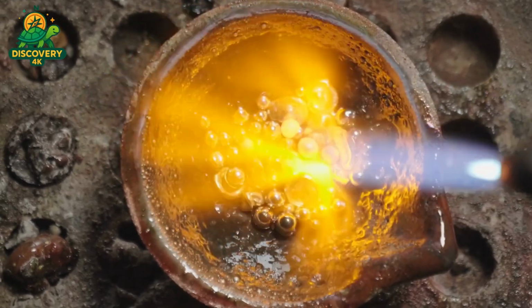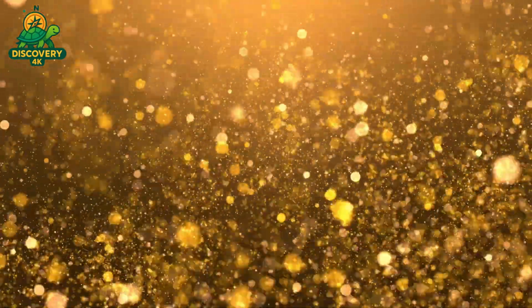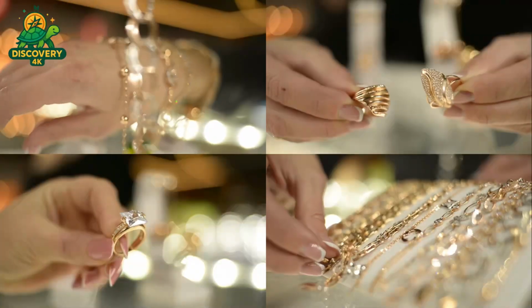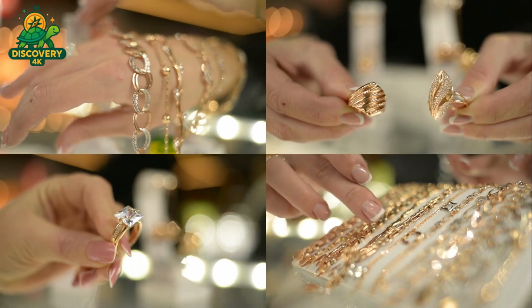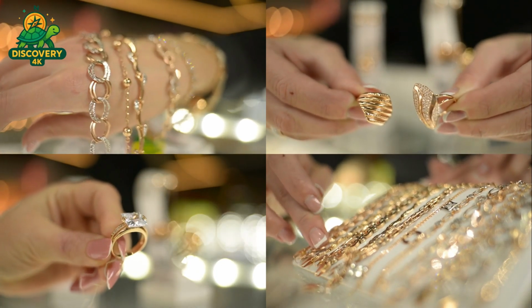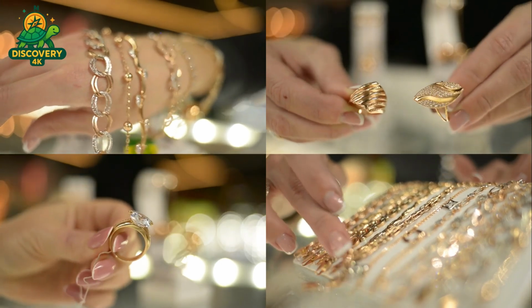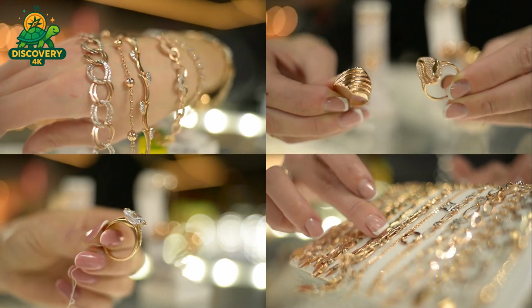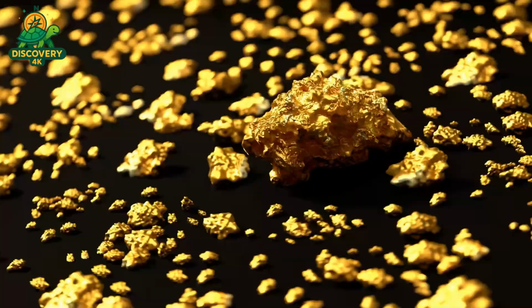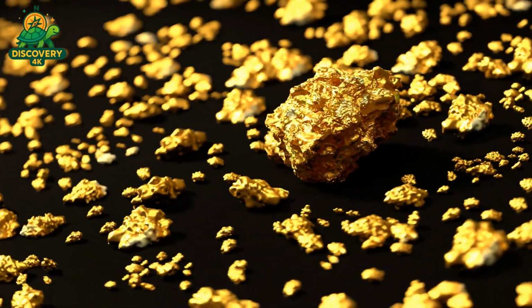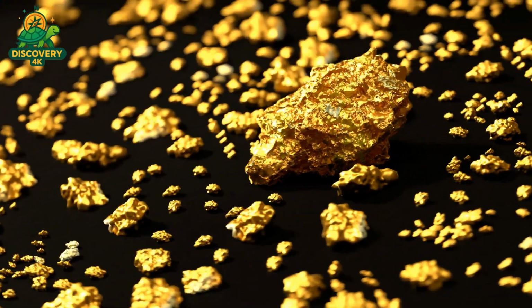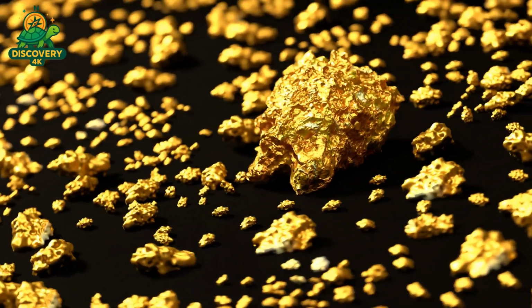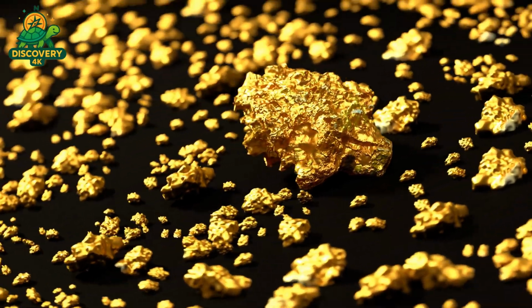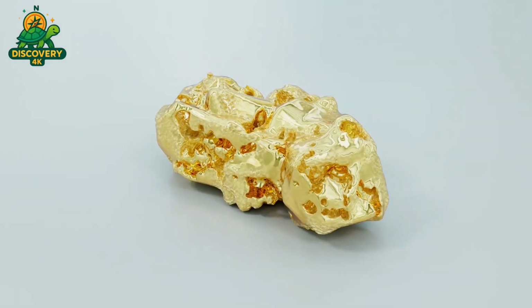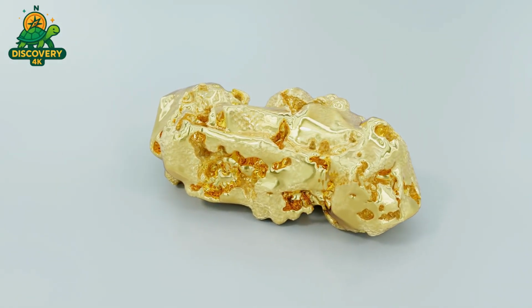The liquid metal is then poured into graphite molds, rectangular, heat-resistant containers designed to shape and cool the gold uniformly. Within minutes, the metal solidifies. The bars are removed from the molds and immediately inspected for defects. Each ingot is then cleaned and tested using X-ray fluorescence, XRF spectrometry, which verifies the gold's purity. The gold is pure, 24-karat gold, 99.99% pure.